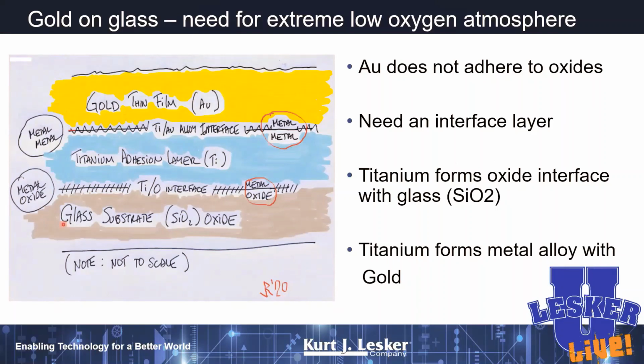So if I want to put gold on glass, for example, glass is essentially a big oxide, and gold doesn't want to stick to oxides. And so if you try to put gold directly on glass, it'll just peel right off. And so you typically use an adhesion layer, something like titanium or chrome. And so if you put titanium, for example, onto an oxide, it likes it because it forms titanium oxide, one of the versions of titanium oxide at the interface, and so that sticks pretty nicely. And then we can put our gold on top of titanium.